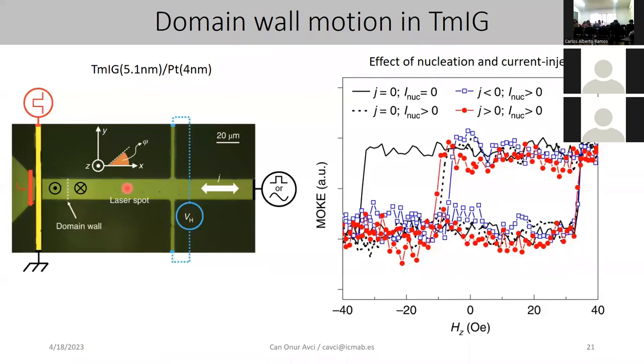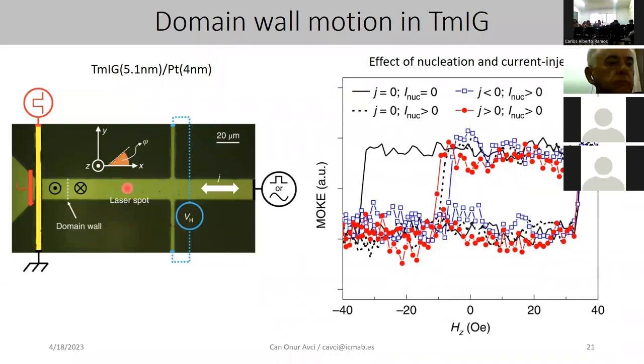We grow our films, and depending on the growth parameters and the substrate itself, even though two substrates are identical, we see that certain substrates show very triangular grains where you get a lot of pinning. Some are like point-like defects. So the grain morphology, or the pinning potential of the sample, depends very sensitively on the substrate. Even between two nominally identical substrates, you can get two different behaviors. And if you slightly change your deposition parameters, you also get different behavior.